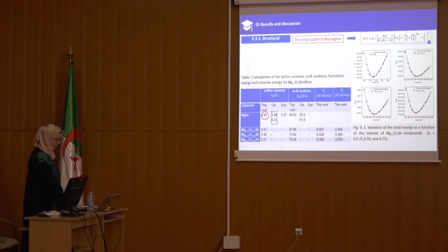The lattice parameter values for binary MgSe are in good agreement with other theoretical works and match the experimental values. In addition, the lattice parameter decreases as the chromium concentration increases, because the chromium atom is smaller than Mg. On the other hand, the compressibility increases as the chromium concentration decreases.